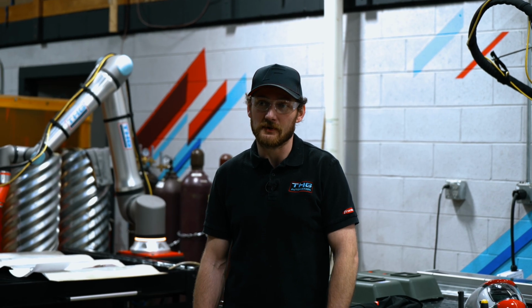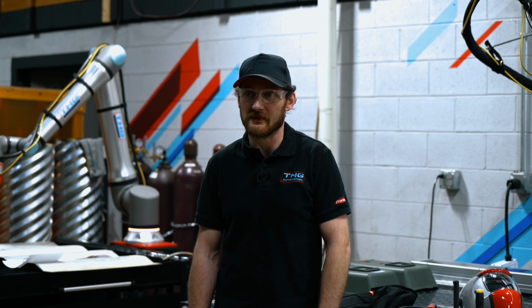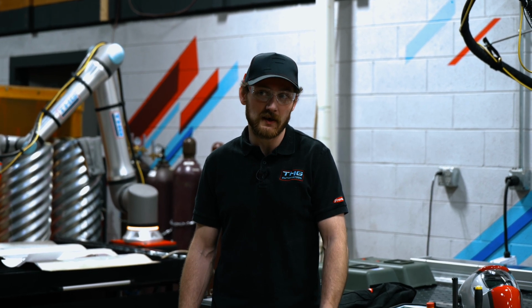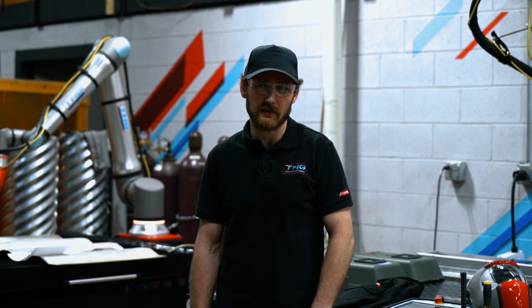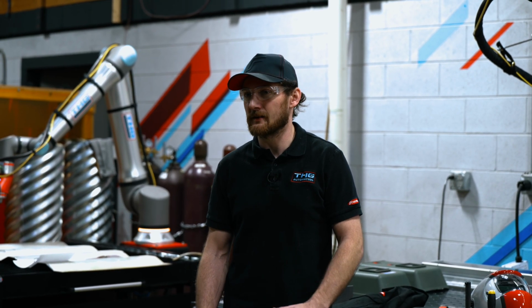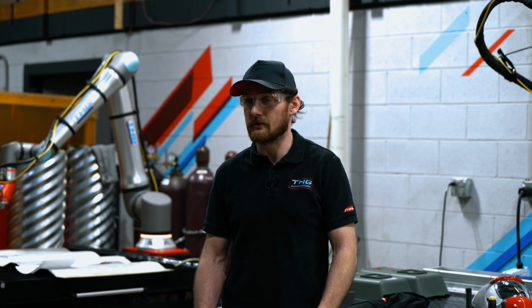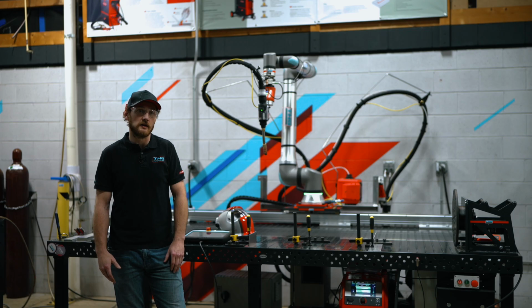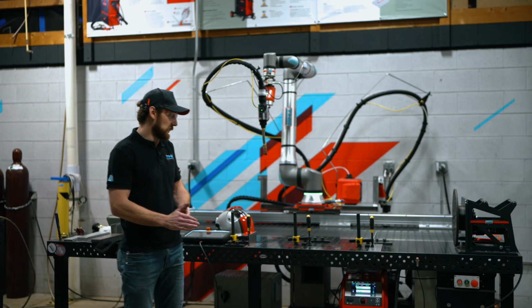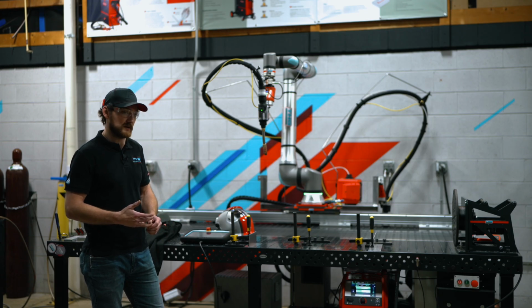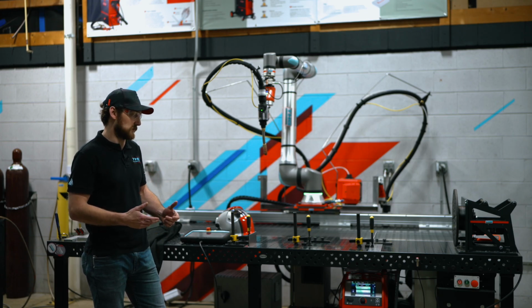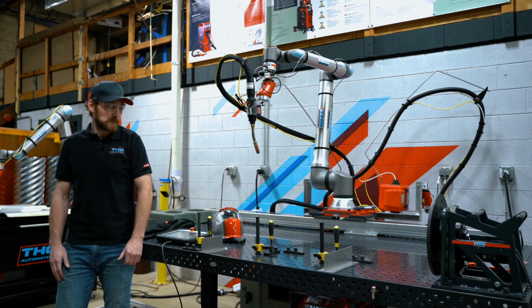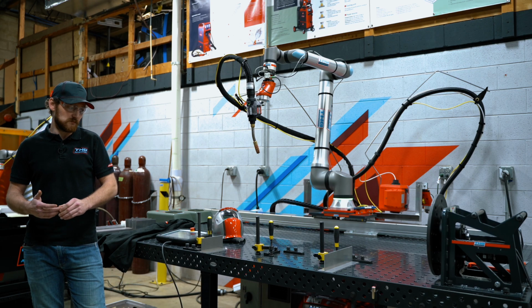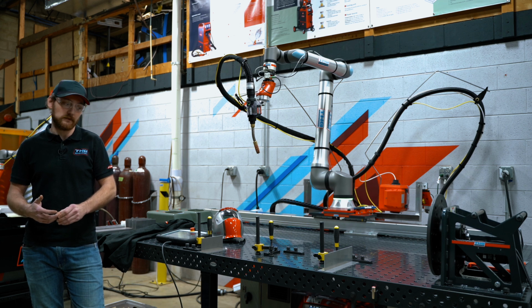More issues that you run into kind of inherently with aluminum as a material is the oxide layer. So aluminum oxide melts at a temperature range that's about 3 times higher than the base material itself. And cracking through that oxide layer is very crucial to a quality weld. With the Fronius equipment, you have hot start and SFI capability, and also with the I-Wave is the addition of AC. With the Fronius equipment, we do have the hot start SFI capabilities to crack the oxide layer.